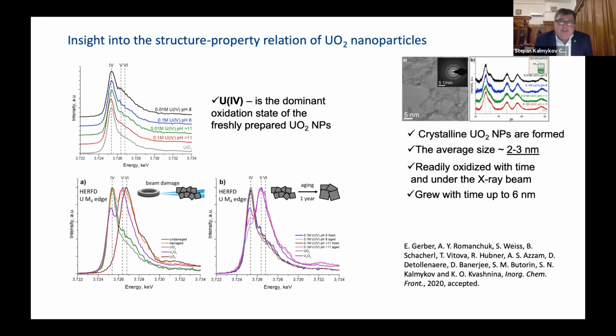We made an experiment under nitrogen conditions, under an inert atmosphere with a very low concentration of oxygen. We made transportation to the ESRF in a special cell, not allowing oxygen to get in there. What we found is that in the freshly prepared sample, the UO2 nanoparticles behave very close to what we have for plutonium. These are 2 to 3 nanometer size oxide nanoparticles with only uranium-4 present.